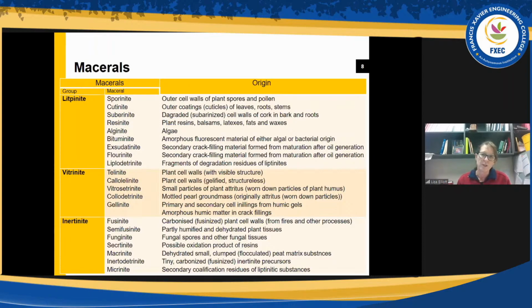It was originally called inertinite because it was considered to be very inert and it really didn't do anything. But in the last 20, 30 years, they've really shown that inertinite has quite a high reactivity, not as high as all of the vitrinite. And so vitrinite and inertinite have been found to actually overlap. The lower, less reactive parts of the vitrinite will be less reactive than the highest reactive parts of the inertinite. But in general, on average, the vitrinite is more reactive than the inertinite. And the reactivity of those materials will change depending on the rank of the coal.